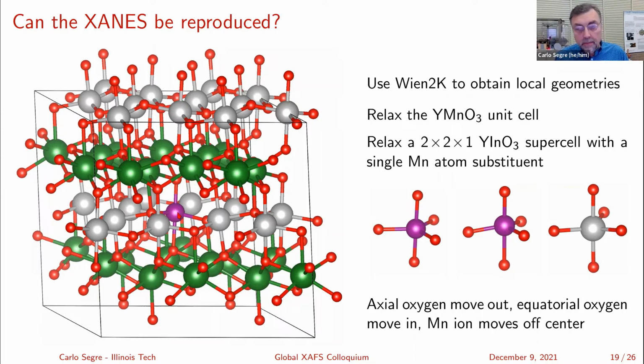When I do the relaxation of doping the manganese in this sea of indium atoms, then I see the following distortions coming in. I get a lengthening of the overall distance between the axial oxygens. They're closer to the indium size than the manganese size. That makes sense, of course. There's a big hole there, and the oxygens are tied into the yttrium on either side, so they'll be farther apart.